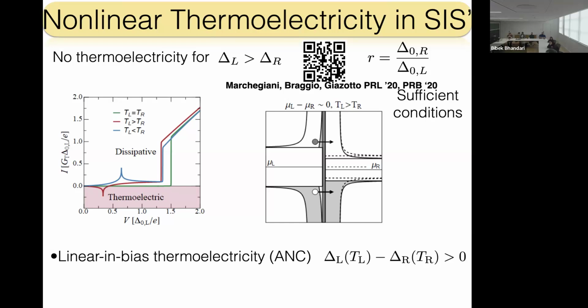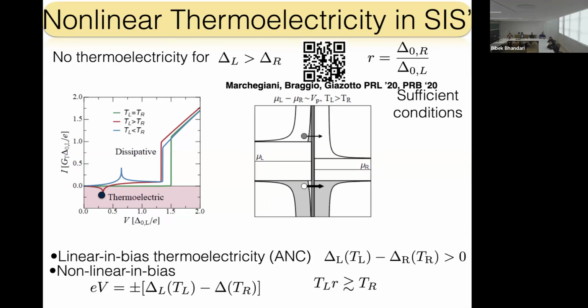So we are in this situation. Indeed, you see that in this case, the red curve corresponds to the thermoelectric behavior, and you see a negative slope. Negative slope means thermoelectricity, and you are in this part because essentially the product between current and voltage is negative. It means that you are producing power, right? Because typically you put the convention that positive IV corresponds to dissipation, and this is thermoelectricity. However, you see that, okay, what happens? Now, if you increase a little bit the voltage, the working point, you can arrive at the maximum.